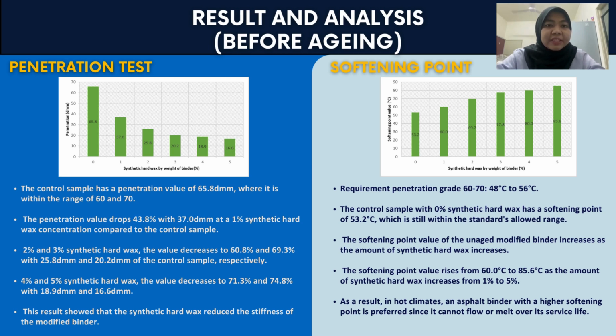The softening point test is conducted to find the temperature at which the asphalt binder turns from a solid to a liquid. The standard requirement for the softening point test is 48 degrees Celsius to 56 degrees Celsius. The graph shows the control sample with 0% synthetic hard wax has a softening point of 53.2 degrees Celsius, which is still within the standard allowed range. The softening point value increases as the amount of synthetic hard wax increases. As a result, in hot climates, an asphalt binder with a higher softening point is preferred since it cannot flow or melt over its service life.